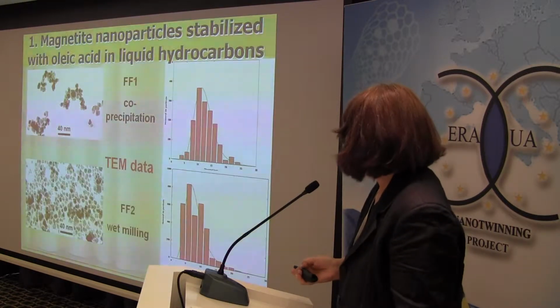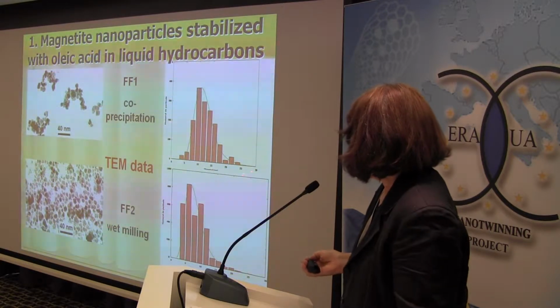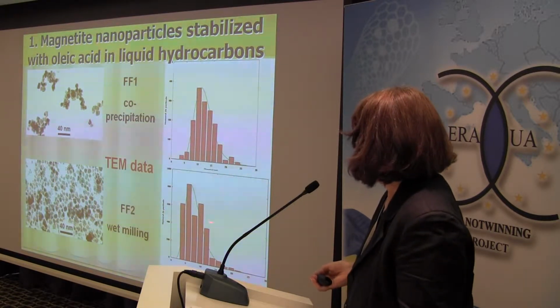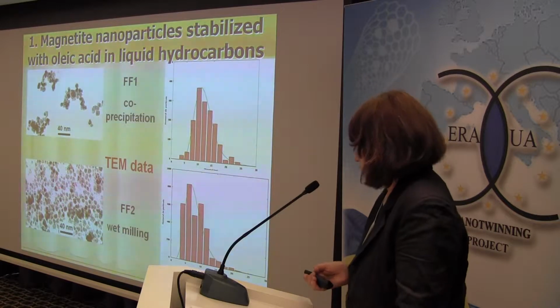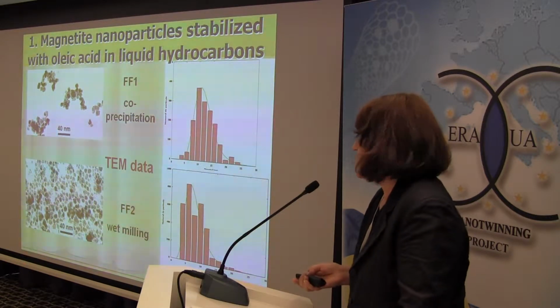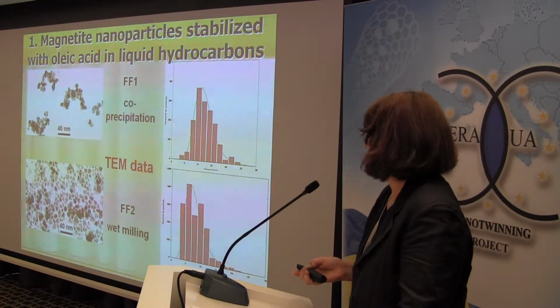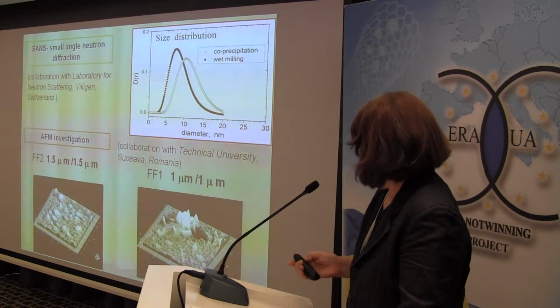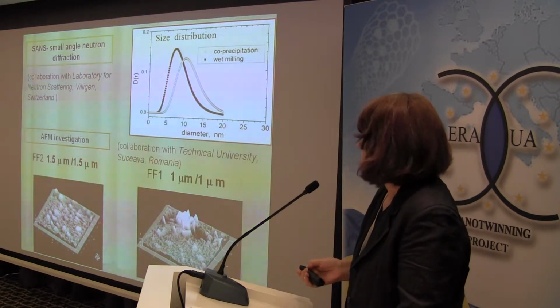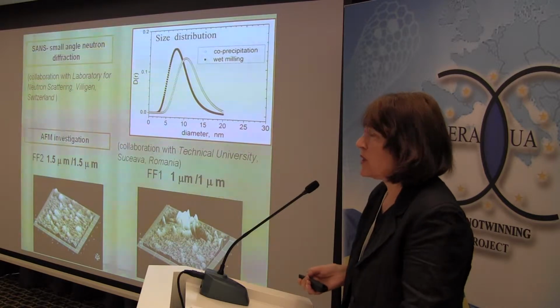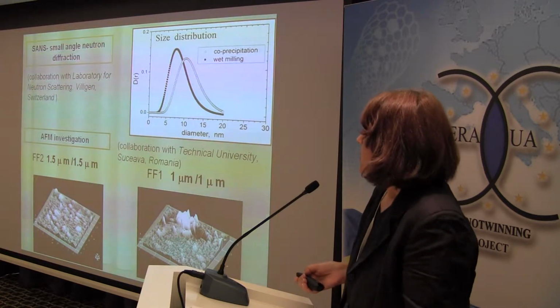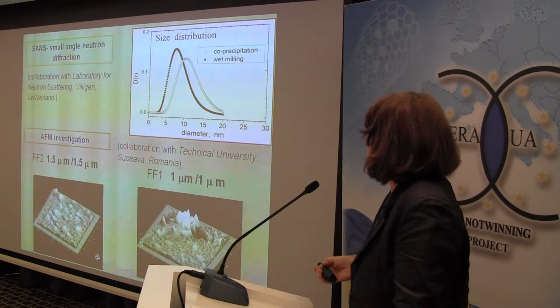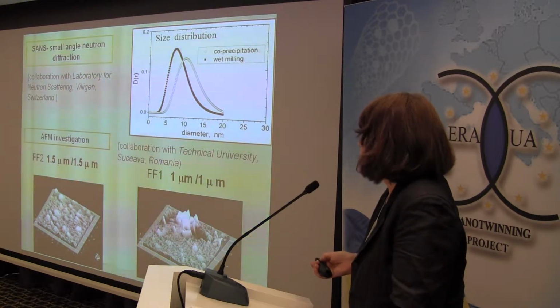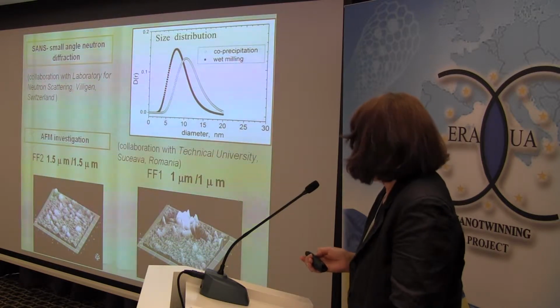Are those large aggregates actually present in our native fluid, or are they only the result of the drying process during sample preparation for the scanning microscopy? The answer was given by small angle neutron diffraction. Our colleague from Hungary, working at that time in Switzerland, was able to do this analysis, and the result is no, they are not present within the native fluid.